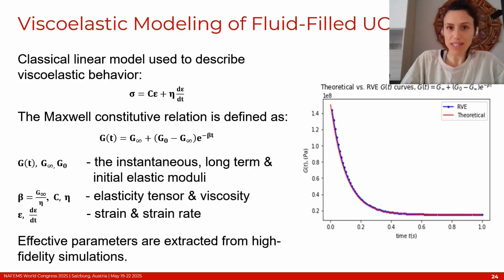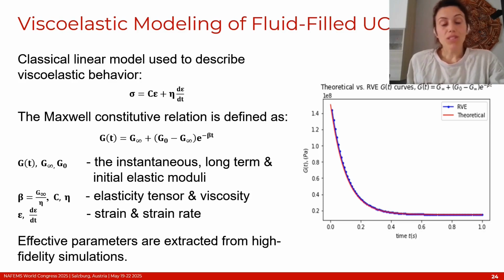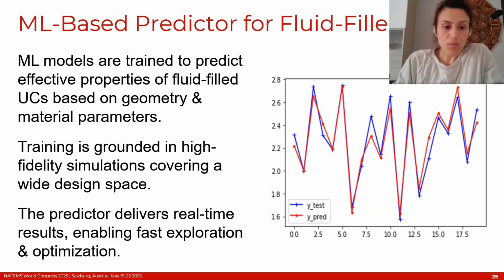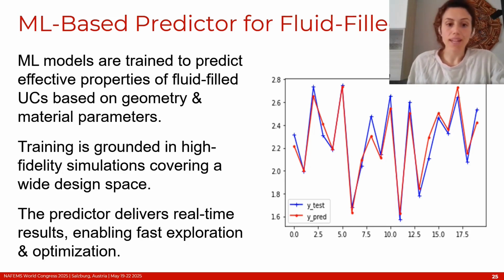Here we see a typical viscoelastic modeling of fluid-filled unit cells using a classical linear model to describe viscoelastic behavior. We can write the Maxwell constitutive relation defining the instantaneous elastic moduli related to the long-term and the initial elastic moduli, and linking also the elasticity tensor, the viscosity, and the strain rates. All these parameters can be effectively derived from high-fidelity simulations to be used then in our machine learning models. We used machine learning models trained on high-fidelity simulation data to predict such effective properties of fluid-filled unit cells. The model delivers near-instant results, making it ideal for rapid optimization and design exploration.